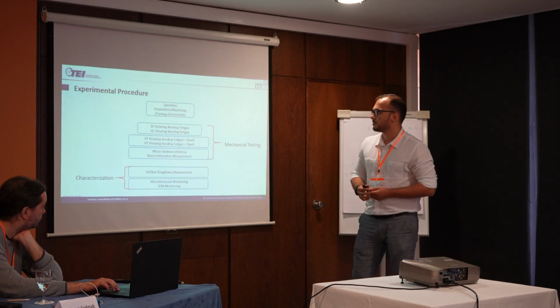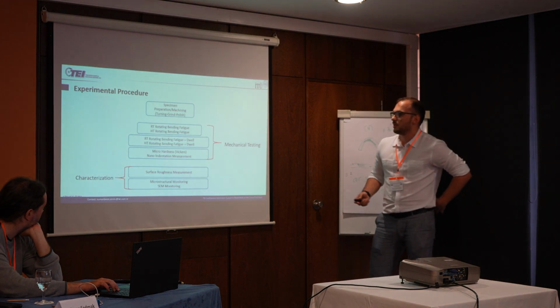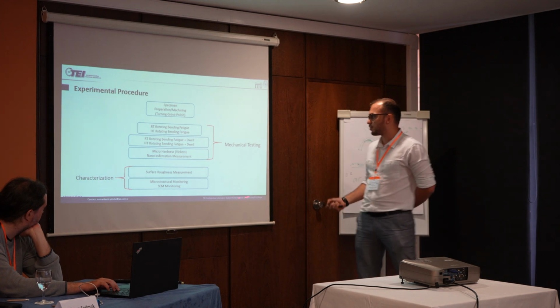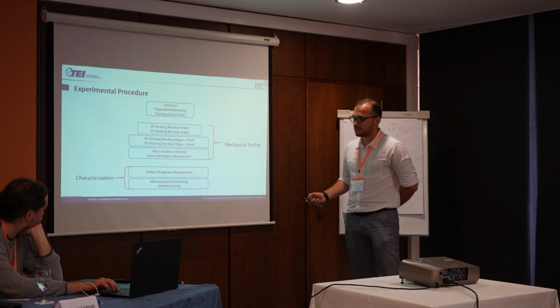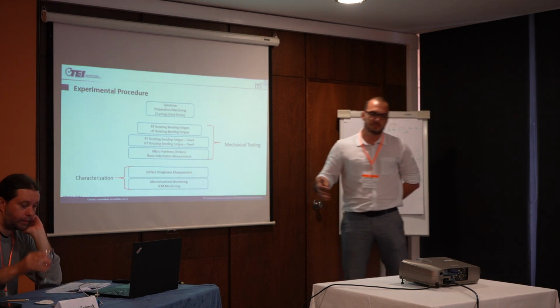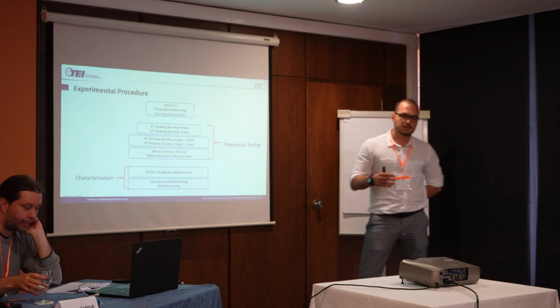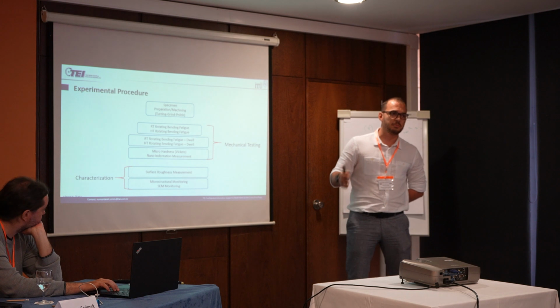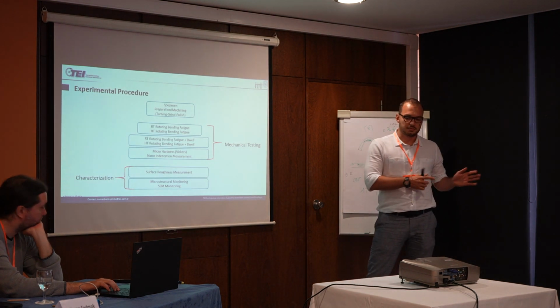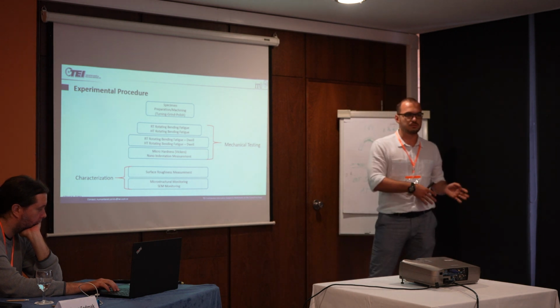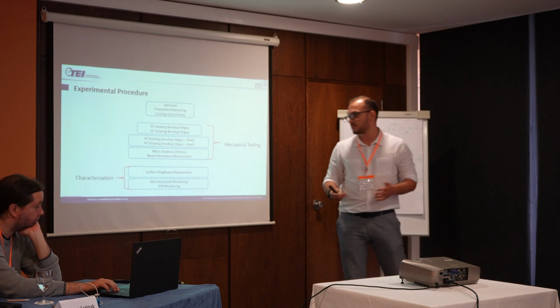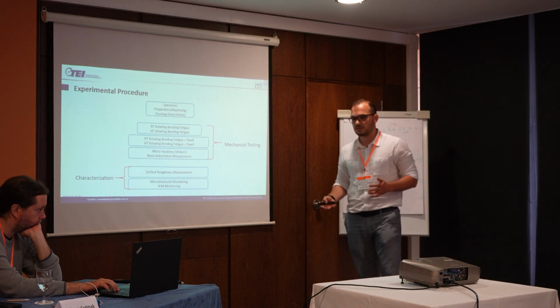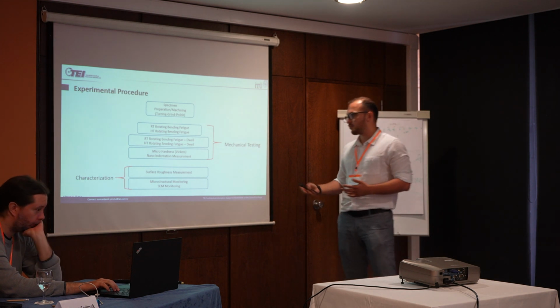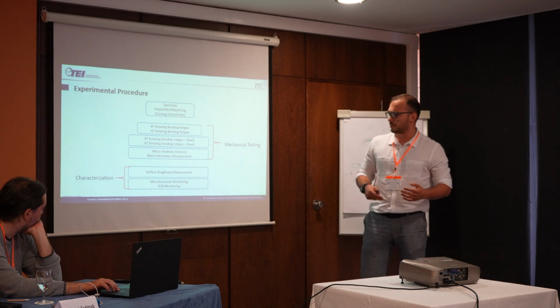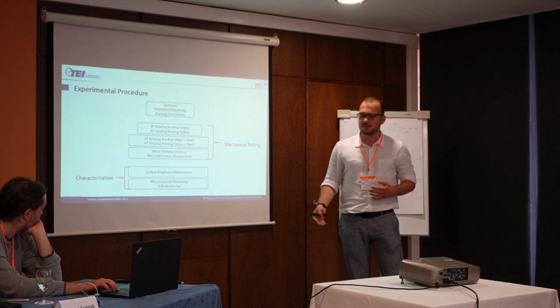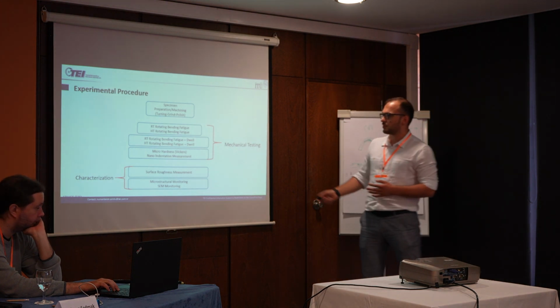We can move on. In our experimental procedure, we divided our work into mainly two categories. First, mechanical testing, then characterization. In the mechanical testing part, we performed room temperature and high temperature rotating bending tests at constant amplitude, and after that we applied the dwells between the cyclic loading periods at both room temperature and high temperature in order to see their effects. After that, in order to understand the phenomena, we performed surface roughness measurements, microstructural monitoring, SEM monitoring, and also hardness and nanoindentation testing.